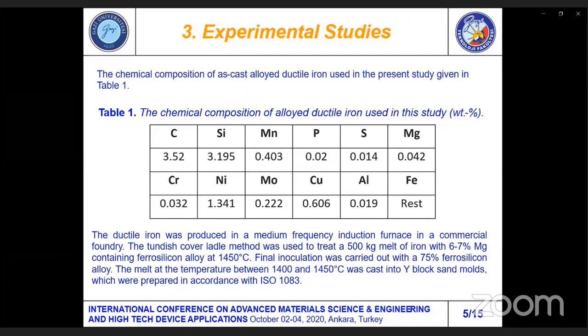Experimental studies. The chemical composition of the cast alloyed ductile iron used in the present study is given in Table 1. The important alloying elements are carbon, silicon, manganese, nickel, molybdenum, and copper. In the present study, we have used alloyed ductile iron in our experimental work. The ductile iron was produced in a medium frequency induction furnace in a commercial foundry. The tundish cover ladle method was used to treat a 500 kg melt of iron with 6-7% magnesium containing ferrosilicon at 1450 Celsius. Final inoculation was carried out with a 75% ferrosilicon alloy.